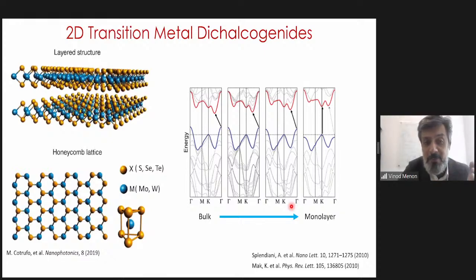So unlike graphene, which is one sheet of carbon atoms, these materials are actually comprised of three layers. There is in this case a molybdenum atom, and the sulfur atoms will be on either side. So it's actually a three-layer system, but each of these is separated by van der Waals force, which means that you can remove one from the next layer using what is now the well-known Scotch tape technique. So you use Scotch tape and you peel it off, and you can get these layers of material.